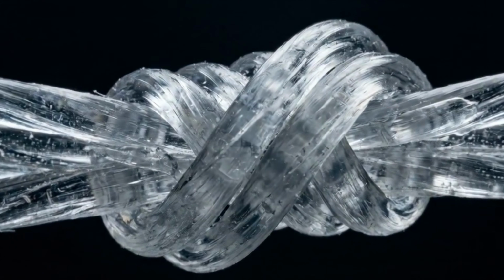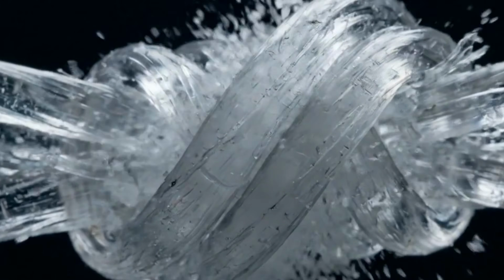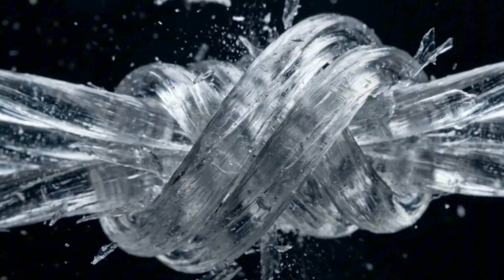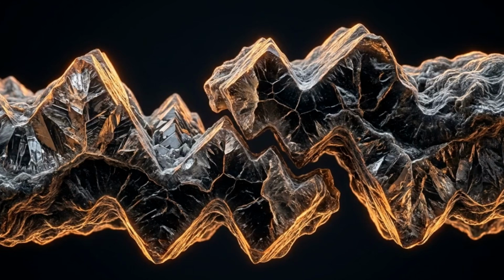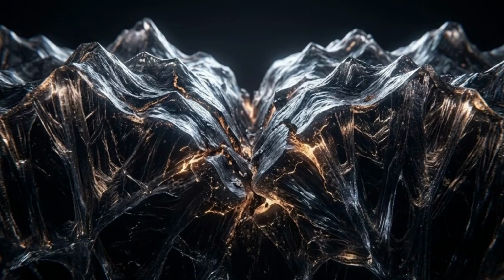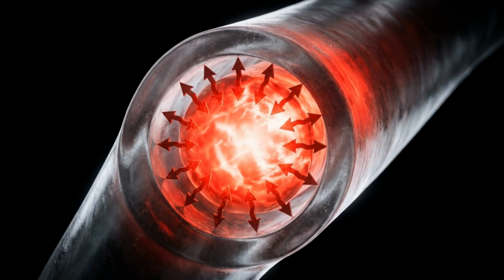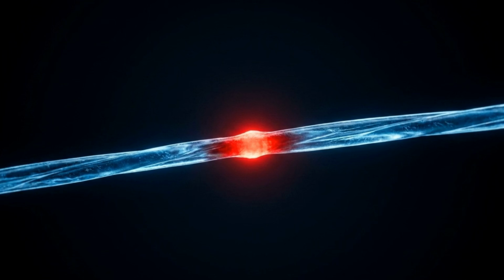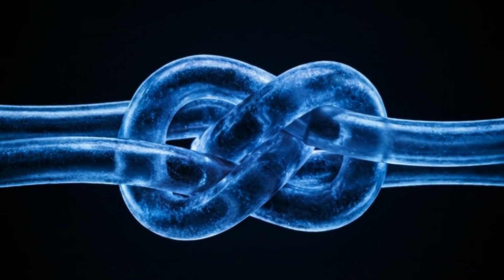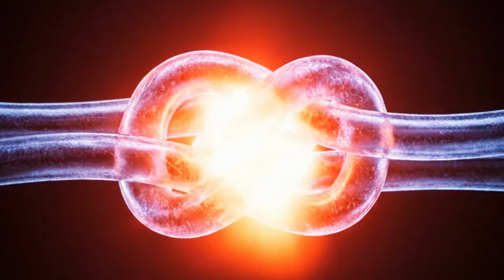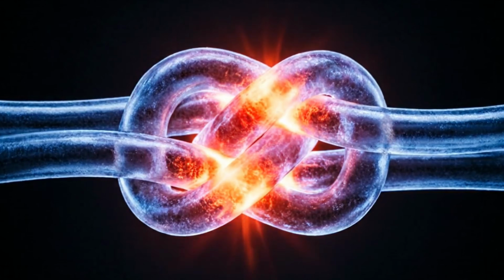This is the dry pull. We see it here as a knot is forcefully cinched without lubrication, grinding the dry surfaces together. This is a tribological event. The polymer strands are sliding past each other while being subjected to those immense contact pressures we just saw. That intense mechanical friction is converted into heat. Because PVDF is such an effective thermal insulator, that heat doesn't bleed off into the air or the rest of the line. It stays trapped right at the interface of the sliding strands, leading to a violent spike in temperature deep inside the core of the knot.